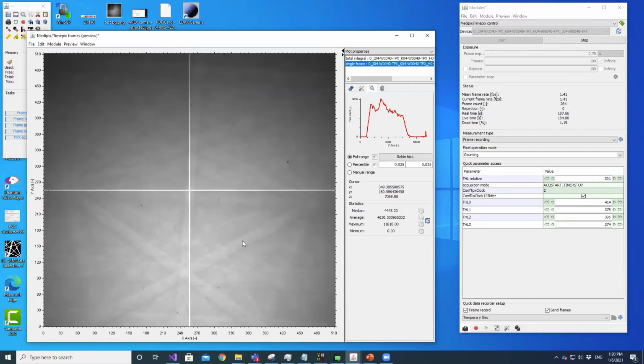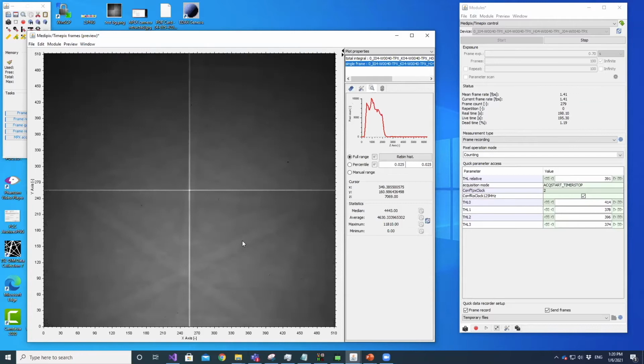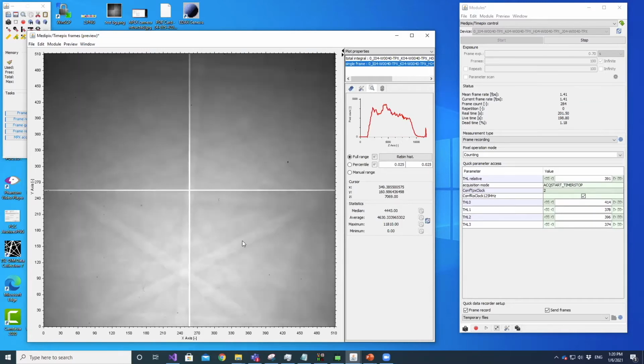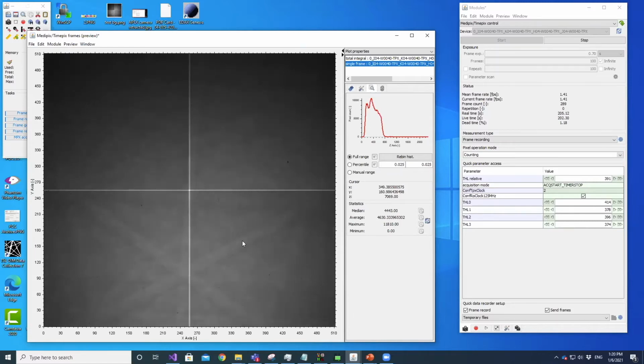But what I want to show, right now I'm running at about 1 nanoamp beam current. I'm going to drop this down about an order of magnitude. So give me 1 second here as I reach over. So this is going to about 100 picoamps. And you can see our image is live, so we haven't changed anything on the collection. But if I refresh my statistics, I've dropped the beam current by an order of magnitude, and the average number of electrons has also dropped by about an order of magnitude. But you can see this still gives us a very recognizable EBSD pattern, even before background subtraction. And I'm assuming by now Shawn has probably said, if you can see the bands, the Hough transform is generally going to detect the bands. And then where it gets really fun is I'm going to drop it another order of magnitude.